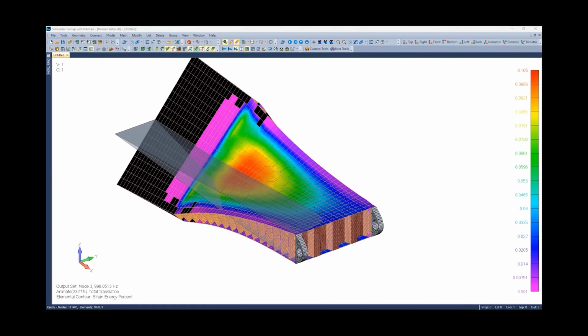Interesting is to see the frequencies around 1 kilohertz. Results were published on similar structures, but rather single beams according to the ASTM standard, just a simple beam as I said, and the results are in the order of magnitude of this value. I was really surprised to see that. One computer just died calculating this, which is a good result. Right, yes, yeah.